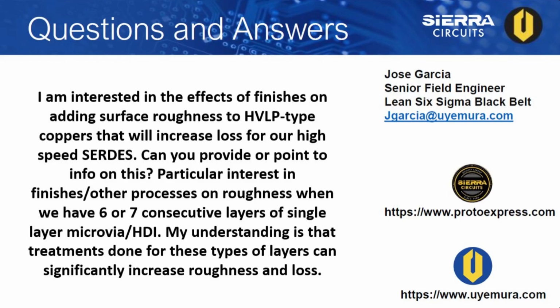Now, on the outer layer, it would be very good to reduce the roughness as well. So you need to make sure you're choosing micro etchants in many cases, like some of the MEC products, where the smallest amount of roughness is imparted in order to get that good adhesion for the fine lines. And the last thing that I know you're familiar with, and maybe you want to comment on this, is the use of peroxide sulfuric as a smoothing and leveling etchant, in order to reduce that roughness. So within the micro etch that you described, we really like to move towards the peroxide sulfurics in order to level out the copper. So those are all the things that you do.